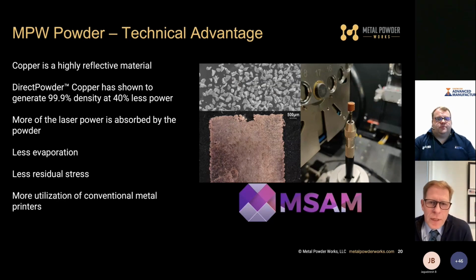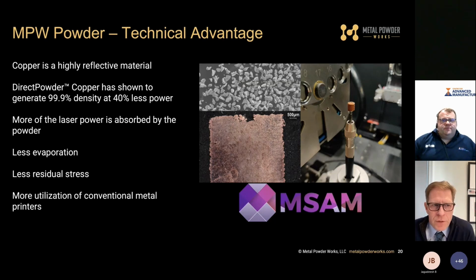What was really interesting is that we've been doing this work with MSAM at University of Waterloo. Copper, as you know, is a highly reflective material. What we found was that we've been able to get to high density, 99.9 percent, but at 40% less power, simply because more of the laser power is absorbed by the particle. It's not reflecting off because we're not making a shiny round sphere. So what this means is that you will see less evaporation inside the chamber. You will see less residual stress in the parts. And from a macroeconomic standpoint, it means that more of the conventional metal printers that are out there can process copper. We're just using a regular laser. It's not a green laser or blue laser or anything like that. We've basically designed a particle that helps the process using laser light.